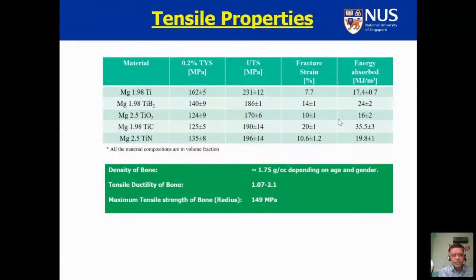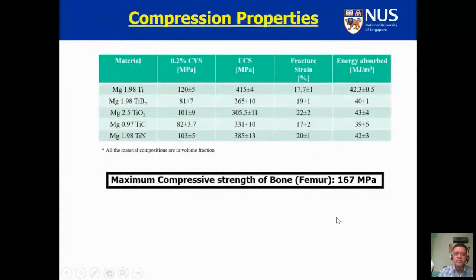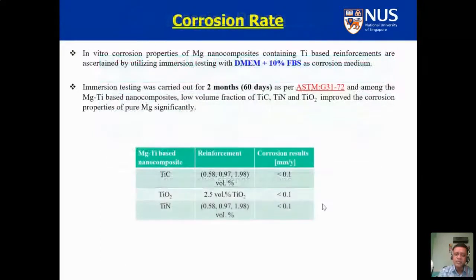So we tried a number of nanocomposites based on titanium, TiB2, titanium dioxide, titanium carbide, and titanium nitride as a reinforcement. The first thing we had to see is whether they have enough strength under the tensile mode. And if you look at the strength of the bone, it is 149 megapascals. The ductility is up to 2%, and all the materials here are higher than that. So that's not an issue. Then we also tried to see how about the compressive properties. Once again, the maximum compressive strength of the bone is 167 megapascal, and all these nanocomposites fulfill that criteria with a very high amount of ductility. So our material, or the magnesium-based material, are actually stronger and tougher than the bone.